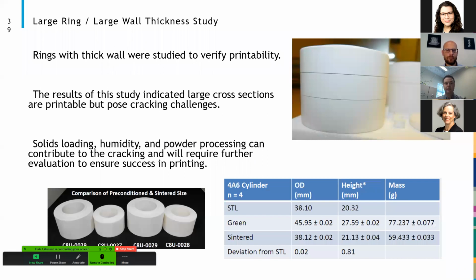The following, after the initial study, was a large wall thickness study. The wall thickness of these components was approximately 8 millimeters in center size, rather large cross sections for this printing capability. But we did observe some potential cracking across the cross section, and it posed significant challenges in dealing with these large diameter components.